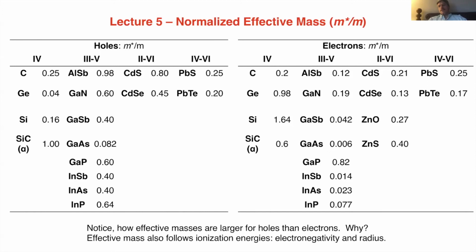So the top of the valence band is going to be made up of sulfur 3p orbitals. And their bonding interaction is going to be weaker than the cadmium 5s orbitals that make up the conduction band, because p orbitals do not make as strong of a bond as s orbitals do.